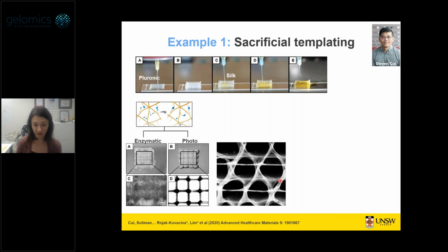And we can use this to get some really intricate structures, and we have lots more examples in this publication. But you can see that using this very simple approach, we can get fibrils of different sizes, different pore structures, shapes and sizes, different spacing between these fibers, so you can get high resolution intricate structures using this relatively simple approach.